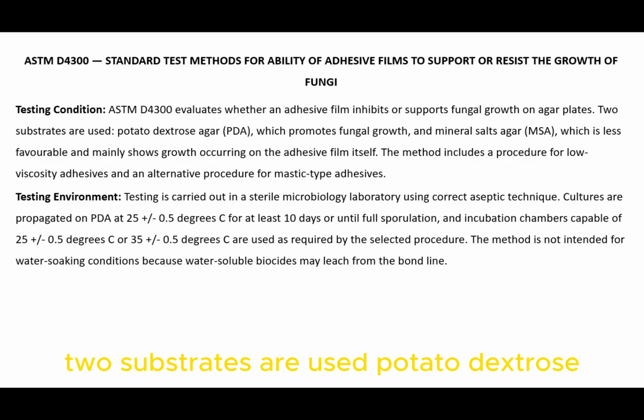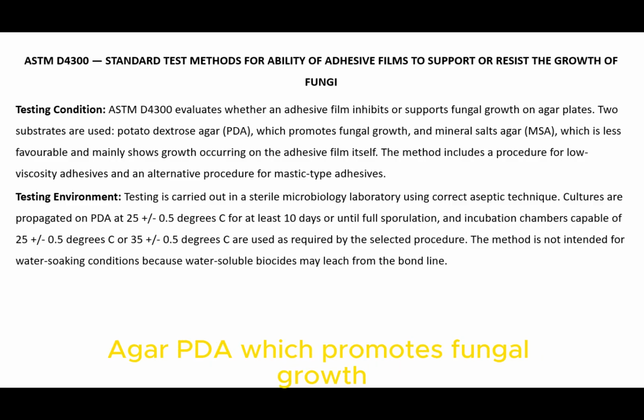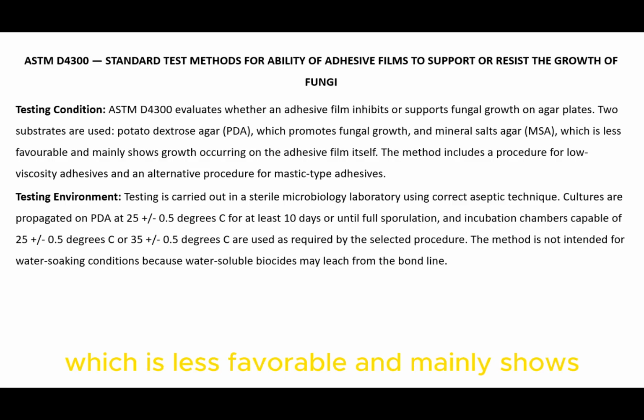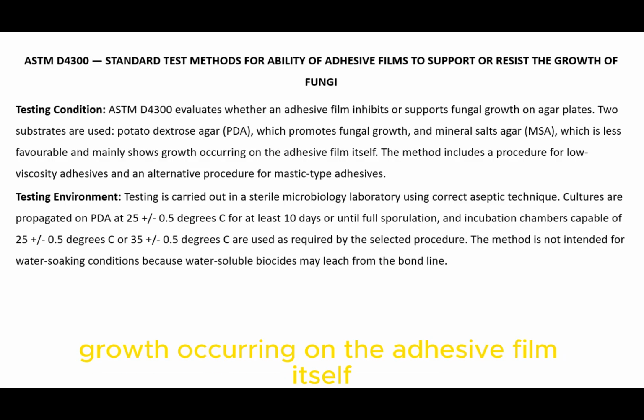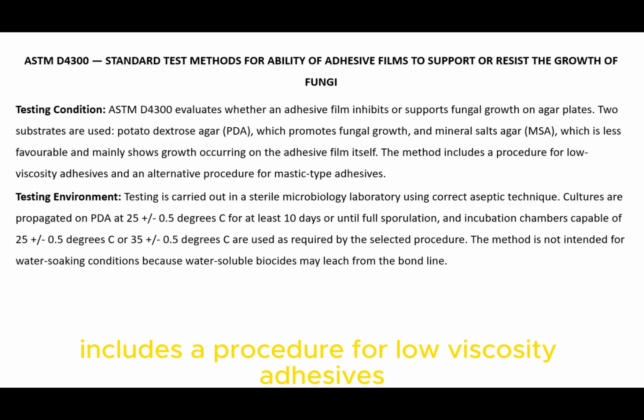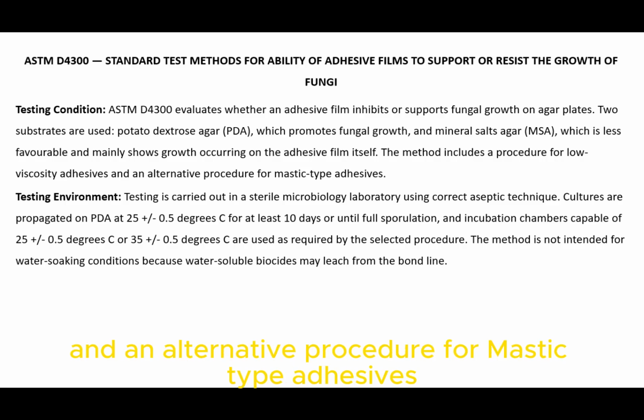Two substrates are used: potato dextrose agar (PDA), which promotes fungal growth, and mineral salts agar (MSA), which is less favorable and mainly shows growth occurring on the adhesive film itself. The method includes a procedure for low-viscosity adhesives and an alternative procedure for mastic-type adhesives.